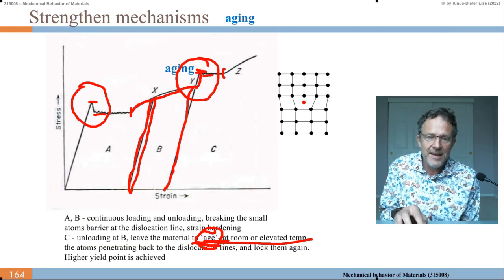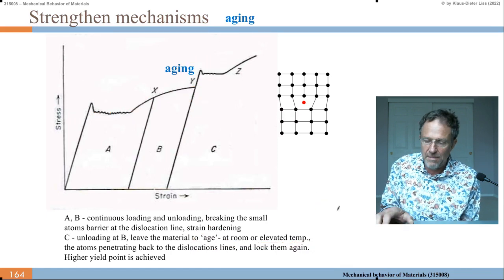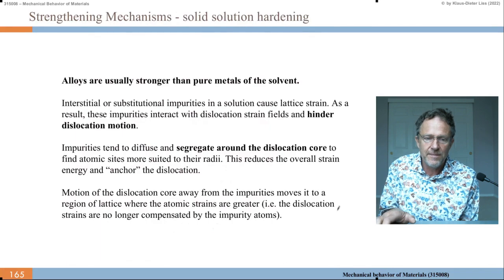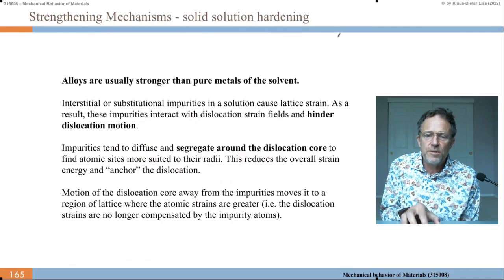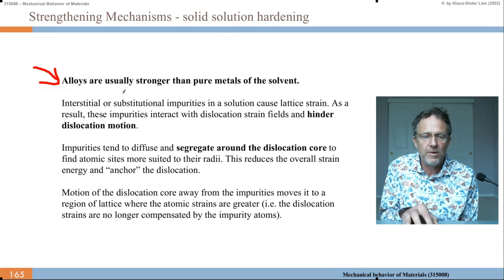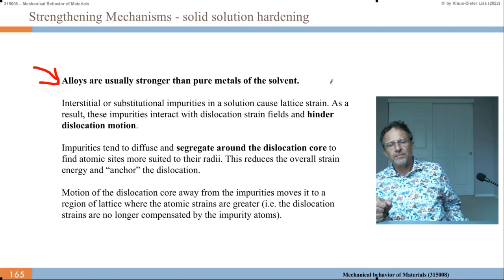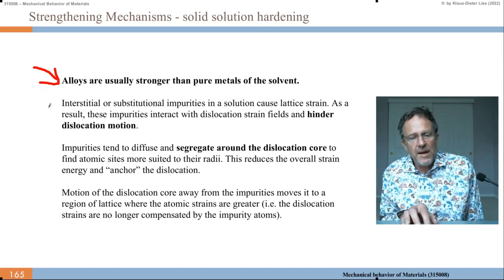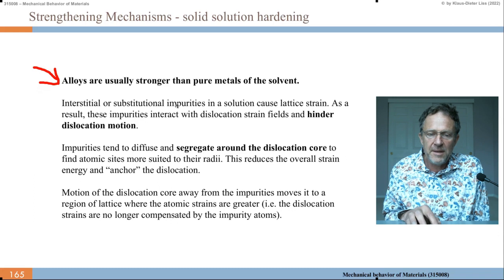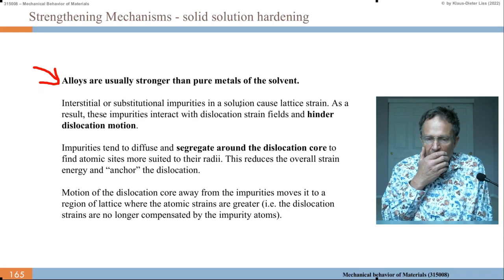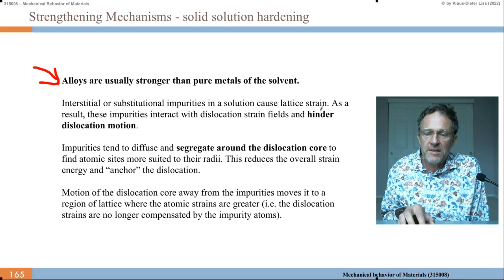So that's also a nice strengthening mechanism. After plastic deformation, we do the aging, which can be at a slightly elevated temperature to enhance the diffusion a little bit. And then we have the solid solution hardening, telling that alloys in solid solution, for example, are usually stronger than pure metals of the solvent. And this is because we have either interstitial, like carbon, or substitutional impurities in a solution, and they cause the lattice strain.